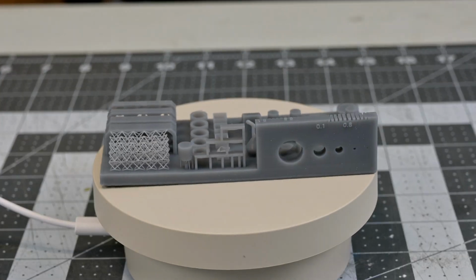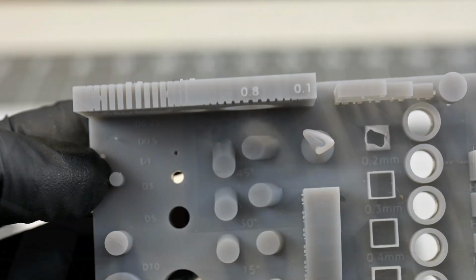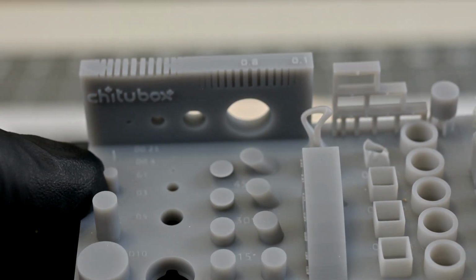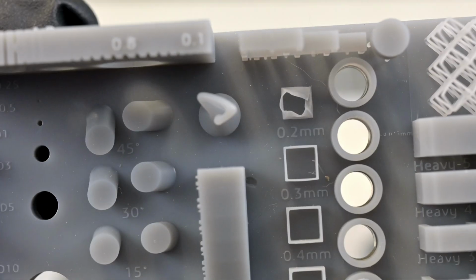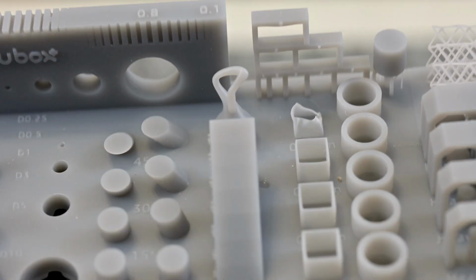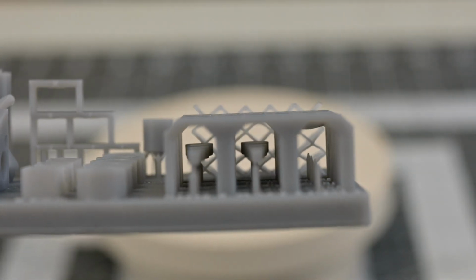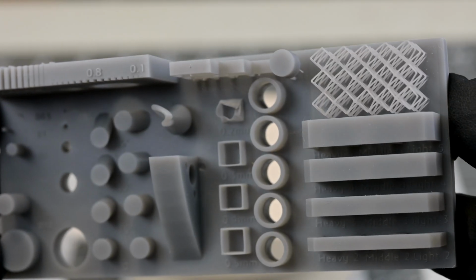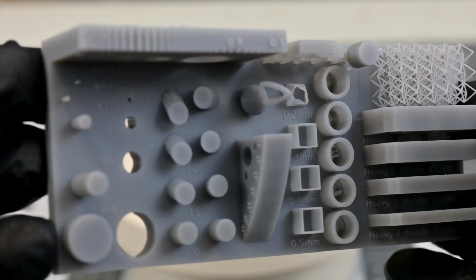tests yourself, but notably the gap test started to close around 0.2 millimeters, and the 0.2mm wall also started to fail. But the bridging test is flawless, and so is the thin lattice work. It failed the 4 light support tests, but passed all 4 medium and heavy supports. Overall, this is a great showing for the Creator Tough.